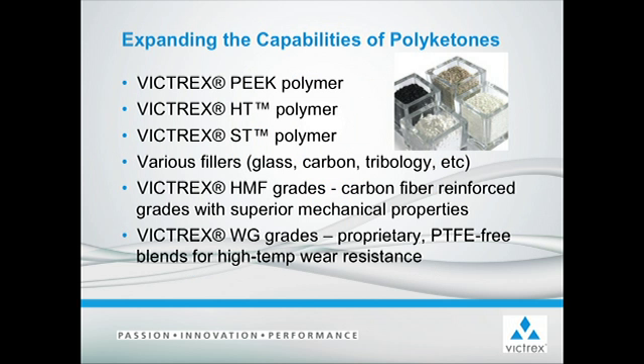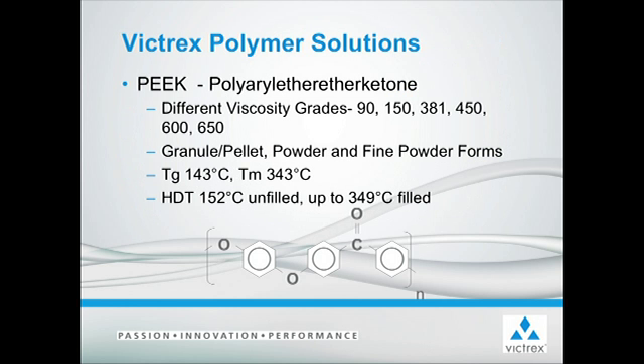The VICTREX portfolio is mainly composed of our PEEK polymer. However, we do have HT and ST polymers, and a wide variety of compounds including glass and carbon fiber reinforced grades, tribology grades for wear and friction applications, HMF grades, which are carbon fiber reinforced products with superior mechanical properties, higher than our standard chopped carbon fiber products, as well as our WG grades, which are proprietary PTFE-free blends for high temperature wear resistance. PEEK, or polyaryl ether-ether ketone, is available in 6 different viscosity grades, ranging from our ultra high flow 90 series to our general purpose 450 range, as well as the extra tough 650 range.